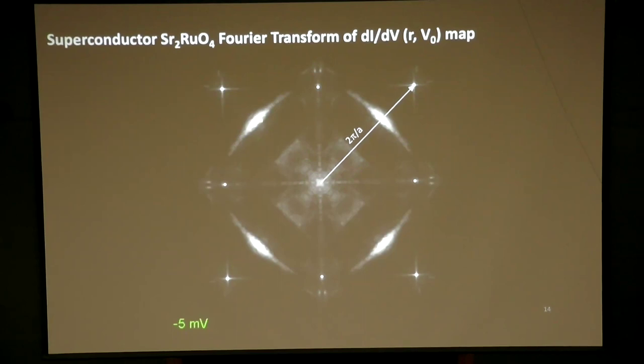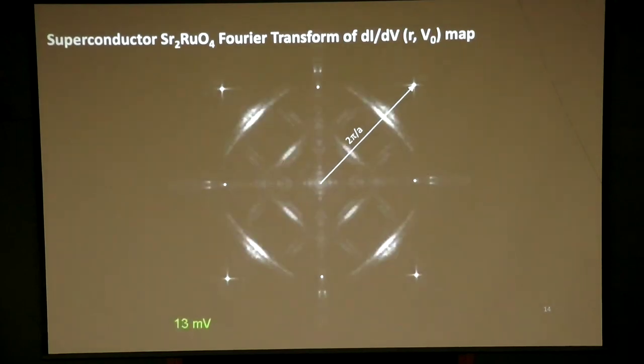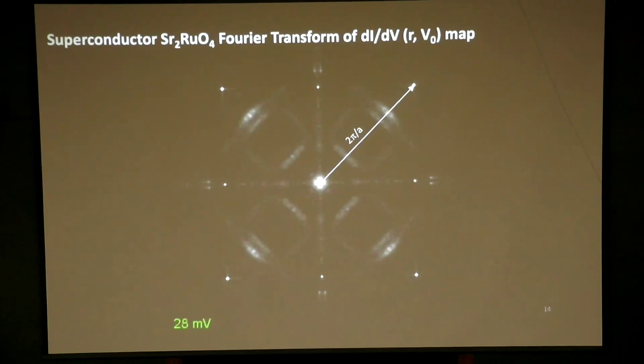In addition, you have these features. This is called quasi-particle interference. It's actually just, in this case, electron interference. And the beautiful thing about this is that it represents the band structure of this very interesting superconductor called strontium ruthenate. And I can show you how this changes with energy. You can see that, similar to ARPES, you can measure dispersion. So this is how the band structure of this material is actually evolving with energy.